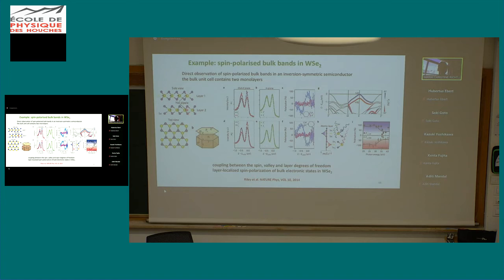Here you see the band structure, and you see that at the K point, you have these two spin polarized valence bands, EB1 and EB2. And by measuring at the K point the energy distribution curve, one obtains these two spectra for right and left scattering. It has been measured with a MOTT detector, and one obtains this polarization. So this polarization is on the same energy scale here.